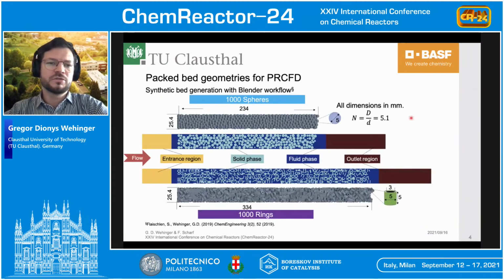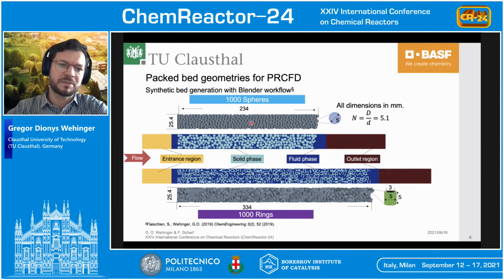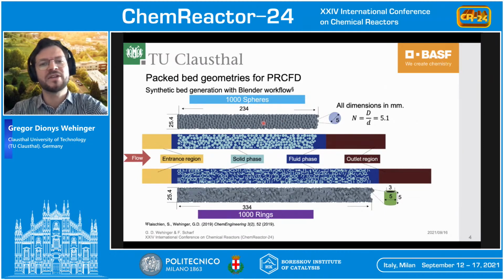So here I show you the 2 different packed bed geometries. So we synthetically generated these packed beds, as you can see here, the packed bed of spheres with the Blender workflow that we published years ago. So these are 1,000 spheres with 5 mm diameter, and we have a D by D ratio of around 5.